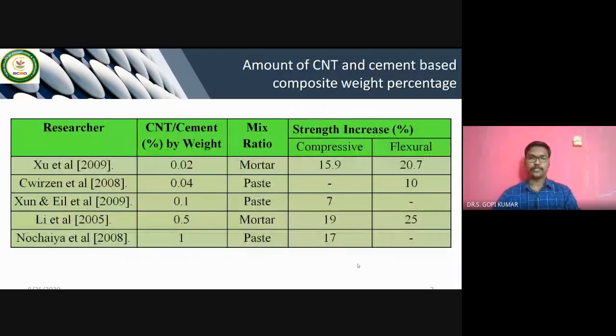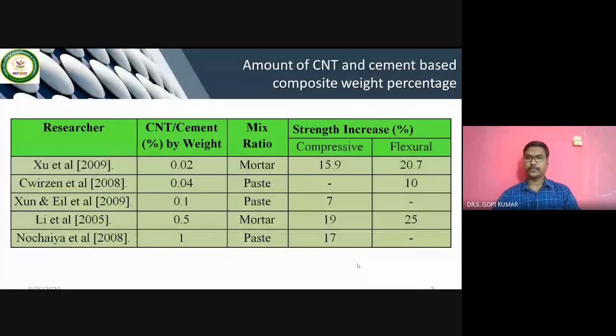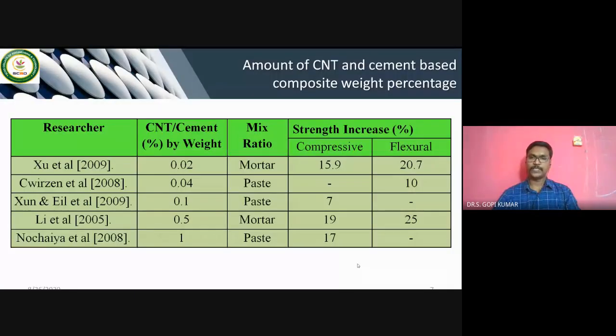And the amount of carbon nanotube and cement based composite weight percentage, where various literature works were presented in this slide, where the compressive strength and flexural strength for varying carbon nanotube cement percentages are represented here, and the highest compressive strength, 19%, is observed with 0.5 percentage CNT and cement weight percentage, where the mix ratio is mortar, and similarly flexural strength 25% higher compared with control is observed.